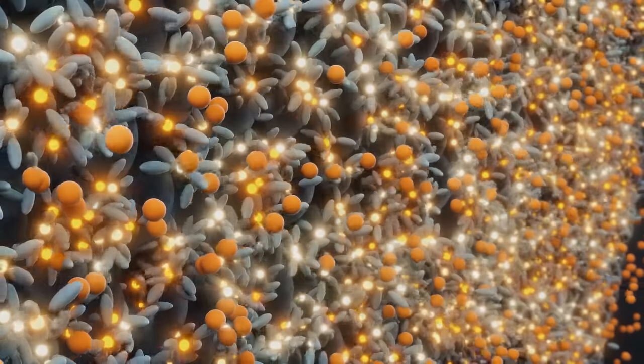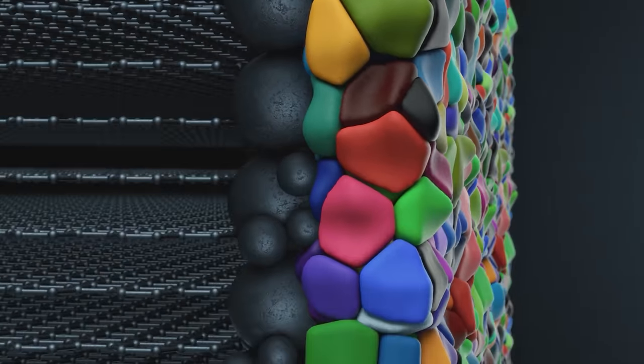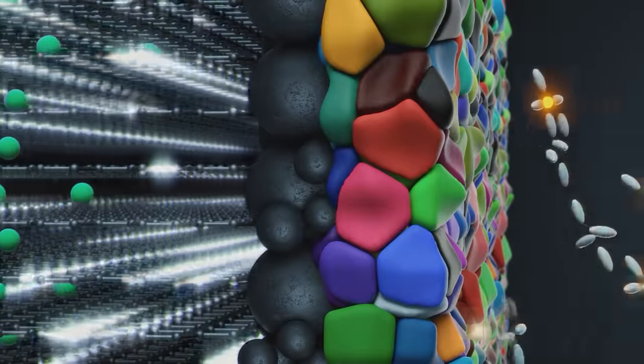Okay, so the way carbonate electrolyte works with lithium is, when it touches the graphite surface, the lithium is going to desolvate from the carbonate, and the carbonate elements will go through some decomposition process and form the so-called SEI on the graphite interface. We had a lot of prior explanation of how the SEI works. Now, this whole process didn't work for sodium. First of all, the desolvation did not happen properly. If you just use carbonate with graphite, using so-called sodium PF6 salt, it didn't work that well. The sodium cannot desolvate from the electrolyte and go into the graphite. This is one of the reasons.